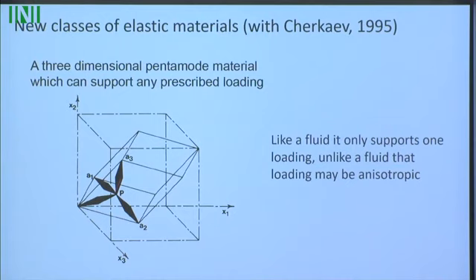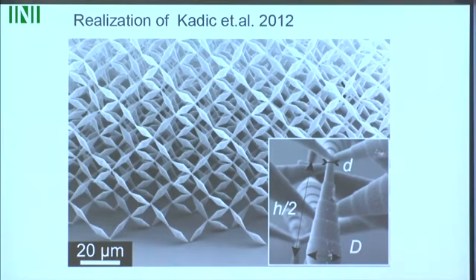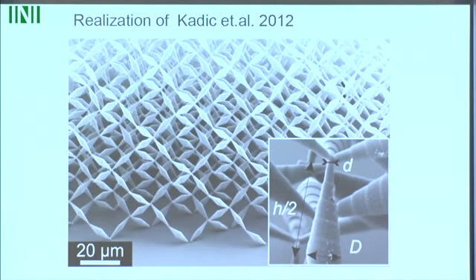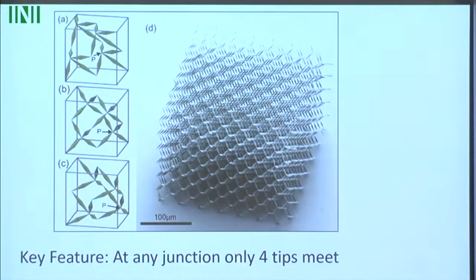It's basically a diamond type structure where you have these double cone elements with tips meeting at a junction here. We actually thought they'd never be made, but that's what the group of Martin Wegener did. You can see this control parameter D. As this becomes smaller and smaller, it becomes more fluid-like. You can also move the point P where the tips meet, and then you get a structure which will support not a hydrostatic loading, but an anisotropic stress.